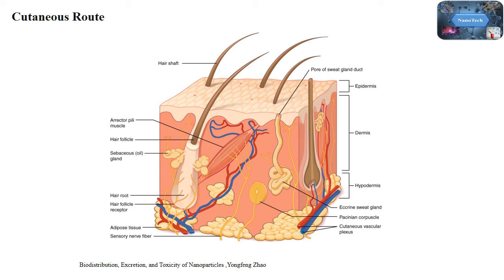Many researchers did investigations of how nanoparticles penetrate through the dermal route. One of the researchers evaluated the penetration of titanium dioxide nanoparticles with size ranges less than 100 nanometers. They determined these particles are located only on the skin surface, on the layer of stratum corneum.